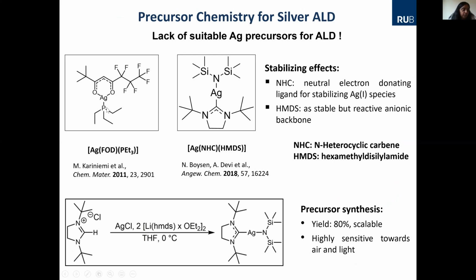But if you closely look at the molecule, you have silver, you have phosphorus, you have oxygen, you have fluorine. All these are actually detrimental for film growth because first of all, you don't need phosphorus and fluorine. They can be a poison in the film if they come as impurities. You don't want any silver oxide forming because of the oxygen here. So one would like to go away from these different elements. But this is the only precursor working. Actually, this is a workhorse in the case of metal ALD, but there was no other choice.